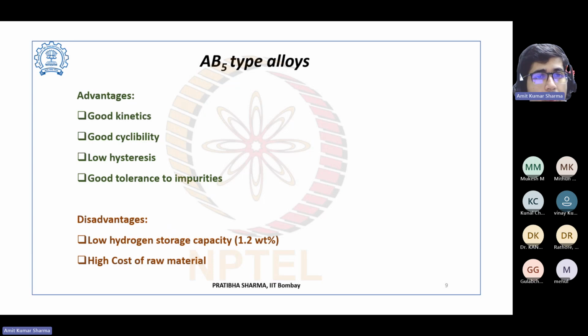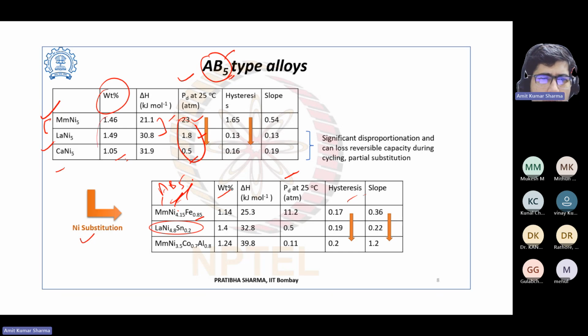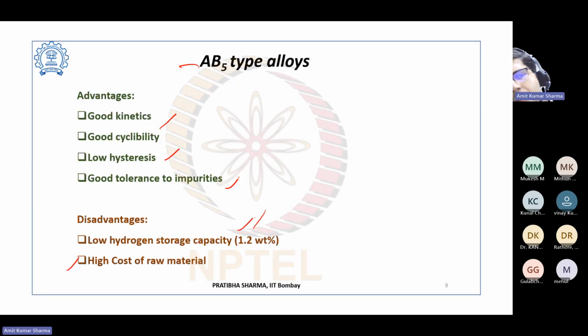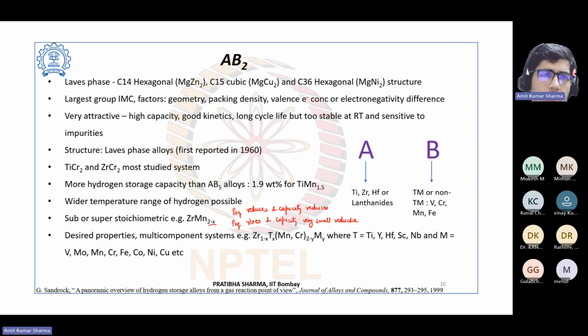So what are the advantages of AB5 type alloy? They have good kinetics, good cyclability, low hysteresis, and good tolerance to impurities. We also have disadvantages: low hydrogen storage capacity, only 1.2 weight%, and high cost of raw material, because A is a rare earth metal, so the cost is very high. The capacity we've seen in the previous slide is only in the range of 1.2 weight%, which is also not good. So these are the disadvantages, but the kinetics are good, with good cyclability, low hysteresis, and good tolerance. Now another alloy is AB2.